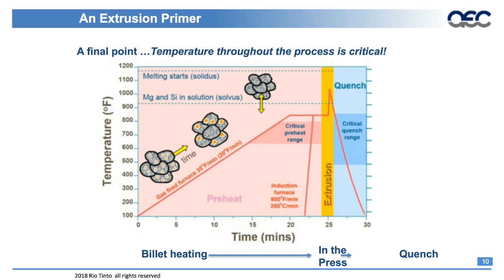It really depends on what the final temper needs to be, also what the alloy is, and then the cross-sectional area of the profile. But obviously we do not want to heat it up so far. If we heat it up around 1,200 degrees, then we would actually melt the profile, and it would basically be scrap at that standpoint. But between the exit of the die itself and, let's say, within the first 10 to 15 feet of the extrusion press, there's going to be a quenching operation.